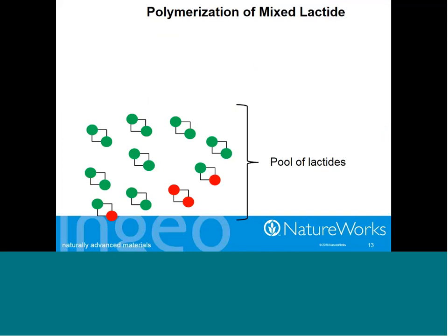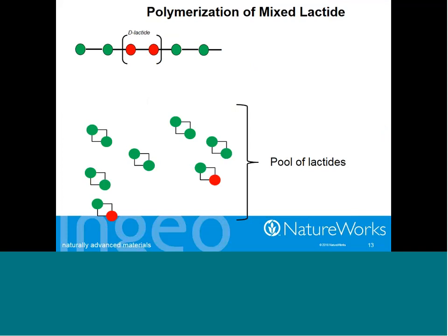The next slide is kind of a cartoon of a polymerization process where you've got a mixed stream of L-lactides, which are the two green dots, D-lactide, which is the two red dots, and mesolactide, which is one green, one red. In the first instance, we've got a D-lactide now isolated between a couple of L-lactides. Generally speaking, D-lactide is always going to be a minor component, and so it will typically be isolated by itself. It will generally not be adjacent to another D-lactide, or even adjacent to a mesolactide necessarily. And then the mesolactide can get incorporated into the chain.